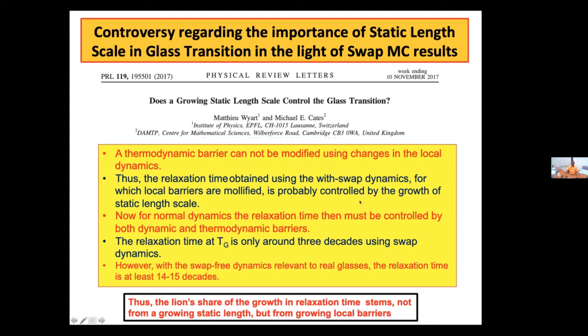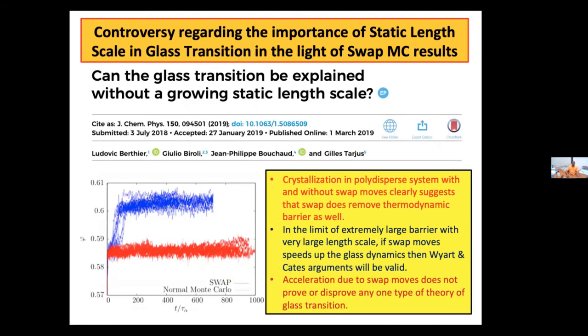This is one big issue that appeared, and it was addressed subsequently by Ludovic, Giulio, Jean-Philippe Bouchaud, and Gilles Tarjus, who argued that even if you look at the crystallization transition of these polydisperse systems, if you do normal Monte Carlo, shown in the red time series, you don't see crystallization. But if you introduce swap, then it crystallizes in roughly 20 to 50 tau alpha time scales. And everybody knows crystallization is surely associated with a thermodynamic energy barrier, which tells you that the swap move can actually nullify thermodynamic barriers to a large extent if the barriers are small in size.